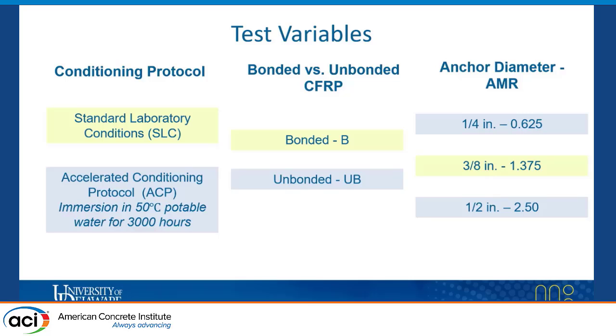This was included in order to mimic complete deterioration of the adhesive layer to assess the performance of the anchors under a case as such. Anchor diameters were also varied in this study between 1/4 inch, 3/8 inch, and 1/2 inch.